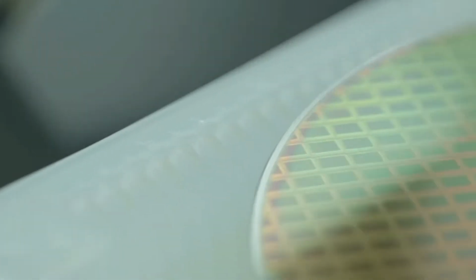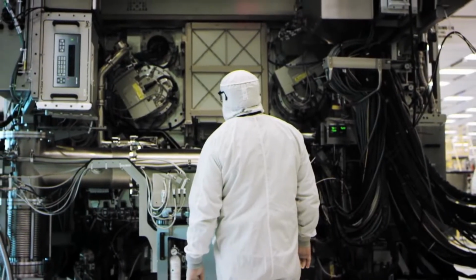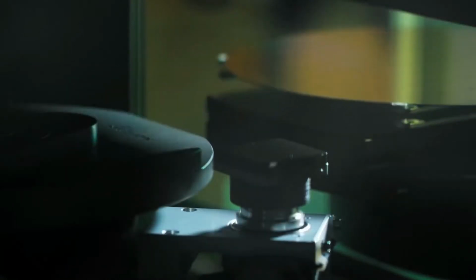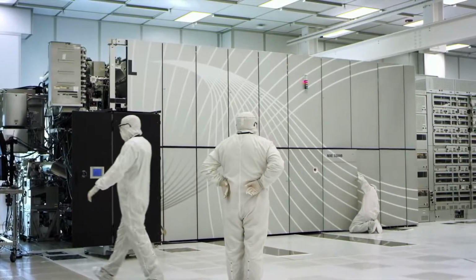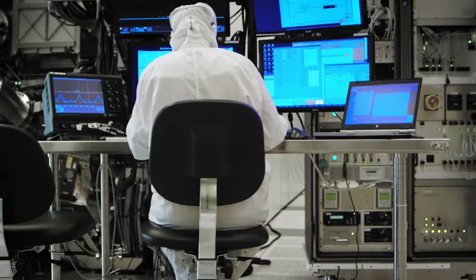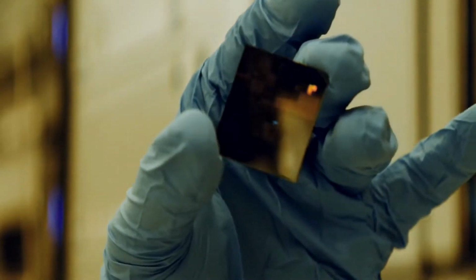Chip stacking typically requires vertical connections between layers of silicon, called through-silicon vias. The layers are usually extremely thin, having a thickness of less than 100 microns. During the production process, each of these wafers is attached to a carrier wafer, which is usually made of glass that is temporarily bonded to the silicon. Once the wafer is processed, the glass carrier is then removed from the silicon with the use of ultraviolet lasers.